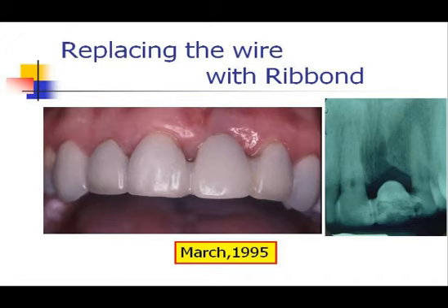And here's the result when the patient left that day we did the replacement. On the radiograph, you can see that the fiber is radiolucent. It's increasing the structural strength of the composite in that interface. We created as best we could the aesthetics between there, bonding to the veneer using silane and roughening the porcelain with hydrofluoric acid as if we were doing a porcelain repair with composite, and we've placed this.